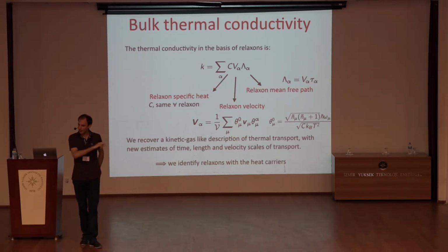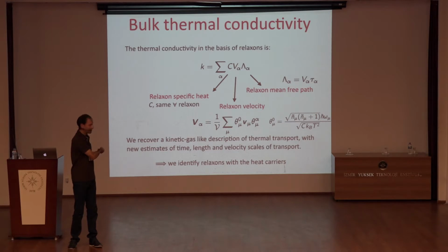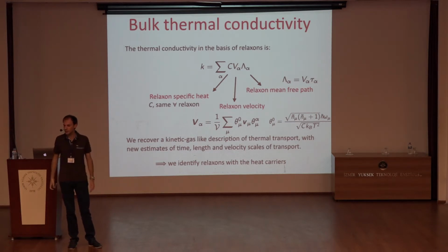Using the form of the scalar product and the metric in the space, which is a detail I'm not entering into, you actually do exactly that, and the average of the phonon energy along these eigenvectors alpha turns out to be the specific heat at constant volume.